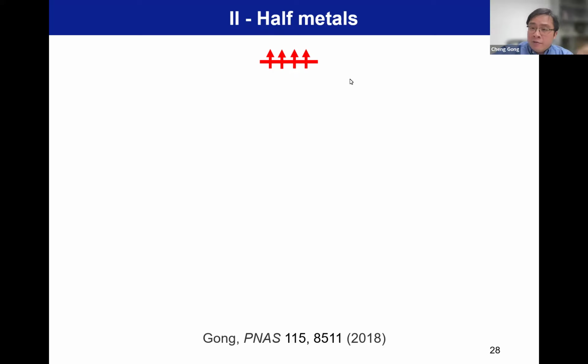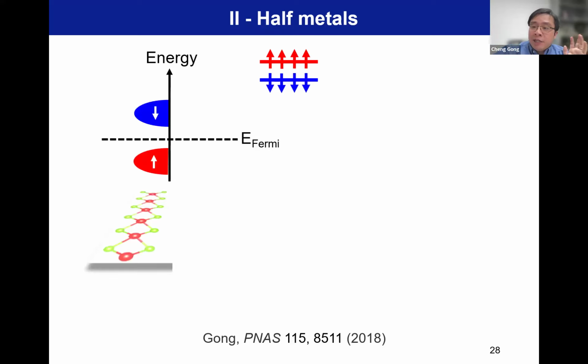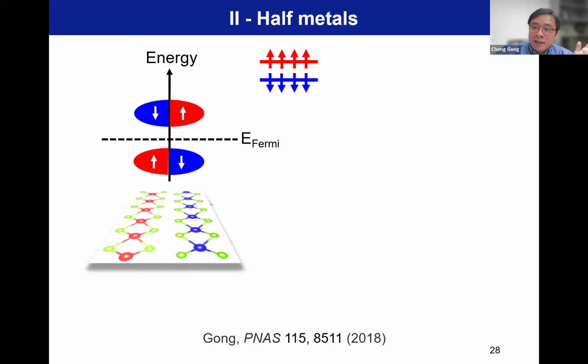If you have a 2D ferromagnet, have another 2D ferromagnet put in this way, either you put them together in this way or they are intrinsically exchange coupled by anti-ferromagnetic interlayer coupling. Anyhow, you have such an A-type anti-ferromagnet. If you look at one layer alone, it's ferromagnet, spin up and spin down bands are split. If you look at the other layer alone, again, they are ferromagnet. But if you look at them together, they are anti-ferromagnets, with zero magnetization.